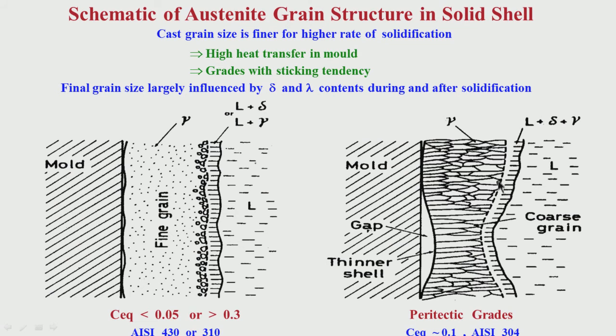Here what happens is at certain locations heat transfer gets affected. So, our mold powder should be such that it gives a mold slag which can control this heat transfer uniformly. So, here the heat transfer control is the main issue for peritectic grades where you have a lot of depressions. Our purpose is to control the depression, through controlling the heat transfer. But for sticker grades, it will try to stick more to the mold, friction between mold and the solid shell is the issue. So, we have to reduce the friction between mold and solid shell.